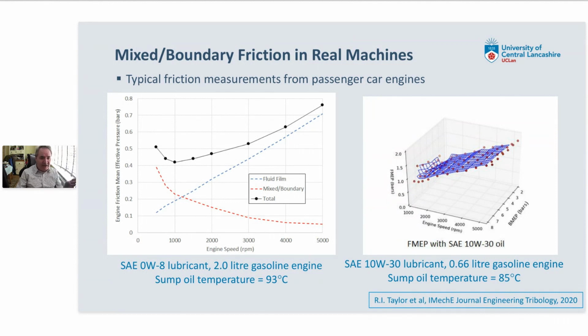What you tend to find is the friction goes up with engine speed, and for speeds greater than about 1500 RPM, the friction simply goes up with speed. And when friction goes up with speed, that's usually an indication you're in the hydrodynamic or fluid film lubrication regime. But if the speed is less than about 1000 RPM in this particular case, we see the friction starts to go up again at low speeds.